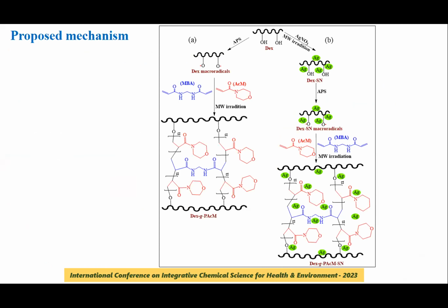This is just to summarize the mechanism. As you can see, the presence of initiator enabled the formation of macroradicals, where the propagation reaction took place by grafting ACM onto the dextran backbone. Thereafter, MBA cross-links two grafted chains to give a three-dimensional network. A similar mechanism happens in the nanocomposite hydrogel. As I mentioned earlier, here the silver nanoparticles are prepared before gel formation.